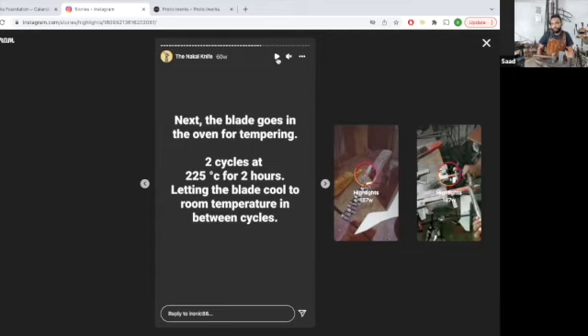So the difference: normalizing is you bring it up to critical and let it cool. Tempering is you bring it up to a certain tempering temperature and you hold that temperature, and at that temperature you let the grain structure of the steel change and propagate throughout the blade. That is called tempering. How do you hold it at 225 for 2 hours in your forge?